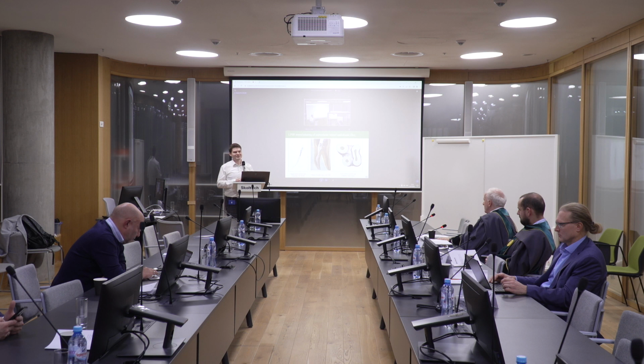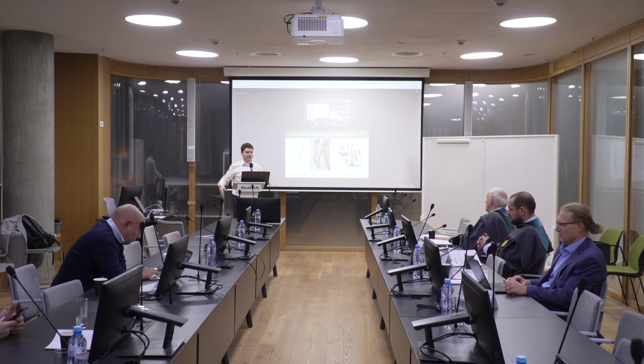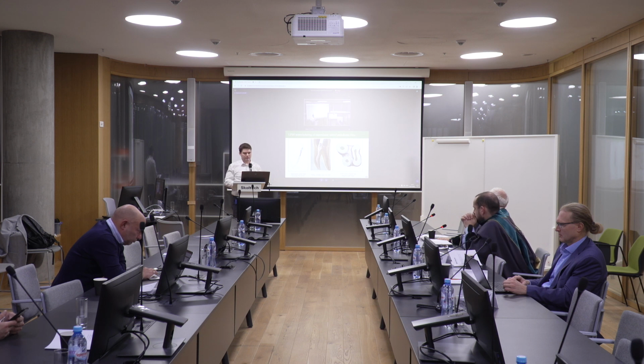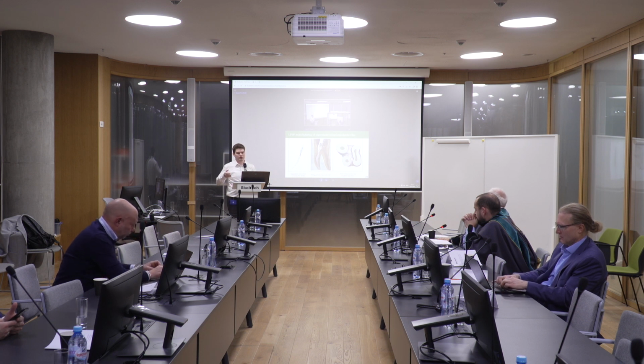No, we can't, because of the many complex phenomena that happen inside the melt pool during laser powder bed fusion. The temperature distribution and the surface area of the liquid domain from which particles are evaporated are all completely different across a broad window of process parameters. That's why a simple evaluation, well, it can be performed, this evaluation based on some Rosenthal model.